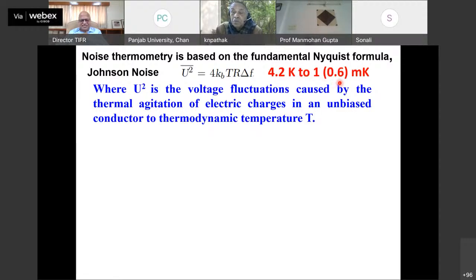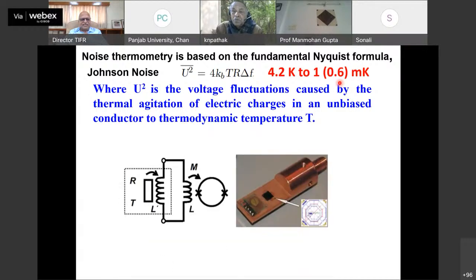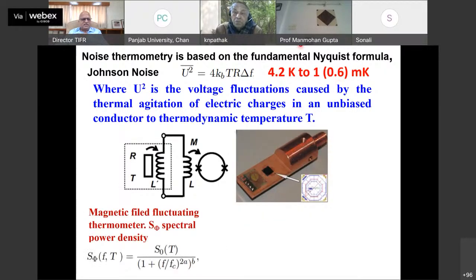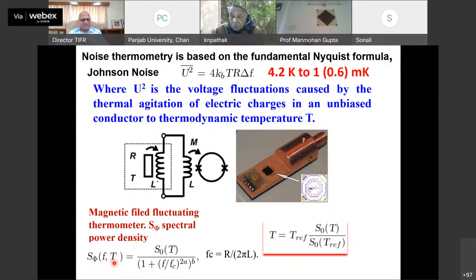Because we have extended the range down to about 600 microkelvin with time. So what we do here is you have a resistor which is inductively coupled to a superconducting transformer, which is again coupled to a SQUID, superconducting quantum interference device, which acts as a current amplifier, and you can measure the noise spectrum, which is given by this expression, and the noise spectrum at finite temperature, the noise spectrum at the reference temperature, and the reference temperature usually is the boiling point of liquid helium. So it requires only one temperature calibration. You can measure down to 4.2K to 1 milli-K.